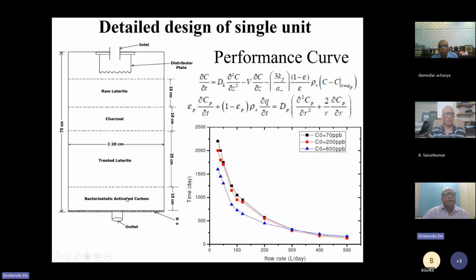Now, before putting this unit in, one has to install an upfront unit for the removal of the iron. All these filters, which basically work on the adsorption principle, need an upfront unit for the removal of iron. Otherwise, in the long term, the iron will be deposited in the actual filter, and the filter will be completely blocked. So iron is removed, followed by the arsenic and the bacteria. And this material is also very good for the removal of heavy metals.